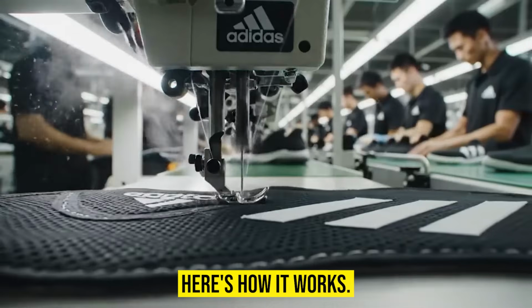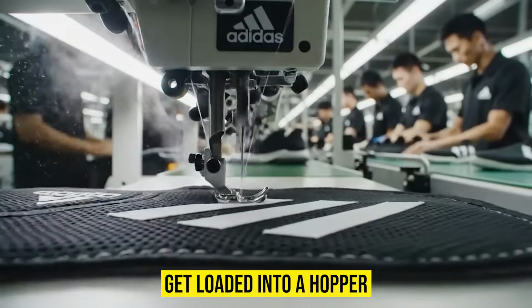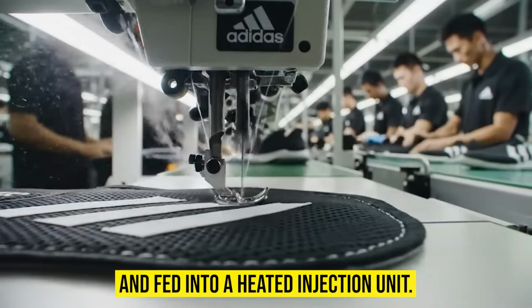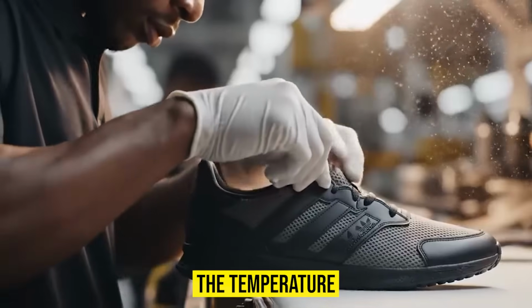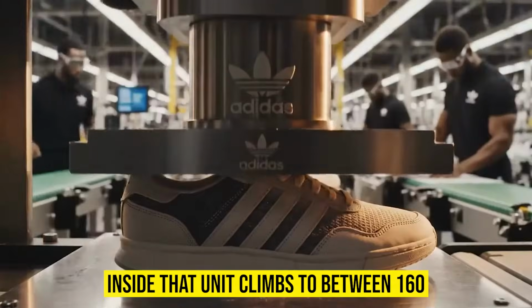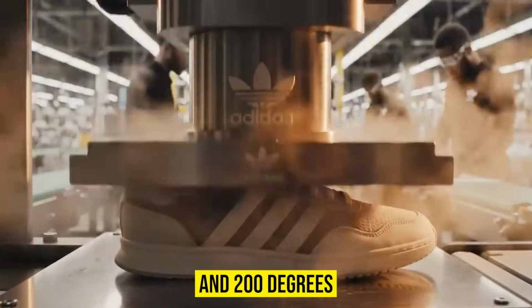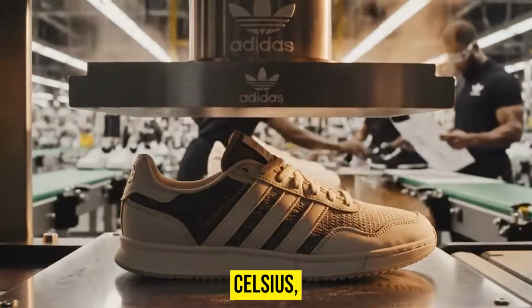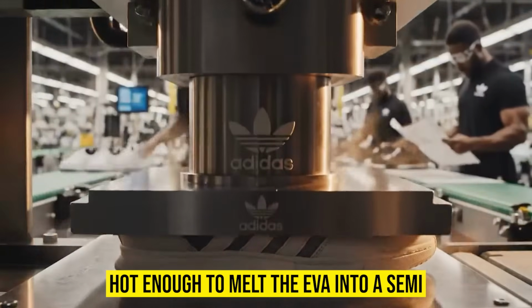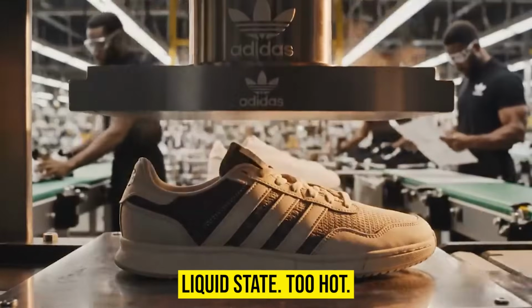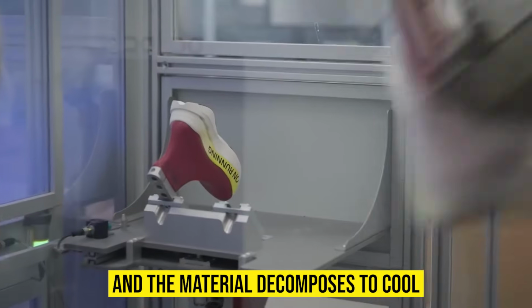Here's how it works. Those EVA pellets get loaded into a hopper and fed into a heated injection unit. The temperature inside that unit climbs to between 160 and 200 degrees Celsius, hot enough to melt the EVA into a semi-liquid state. Too hot and the material decomposes. Too cool and it won't flow properly. The temperature control has to be absolutely perfect.